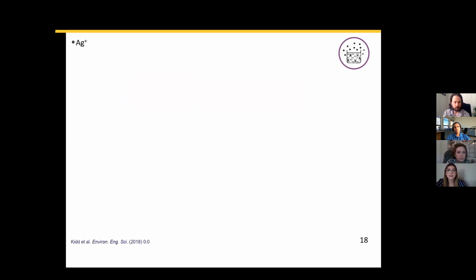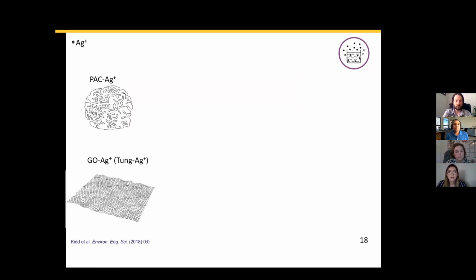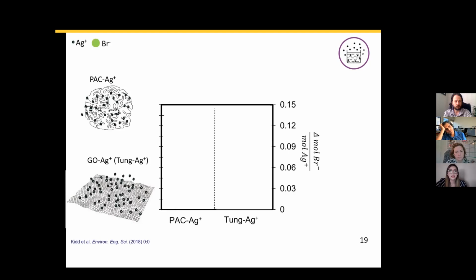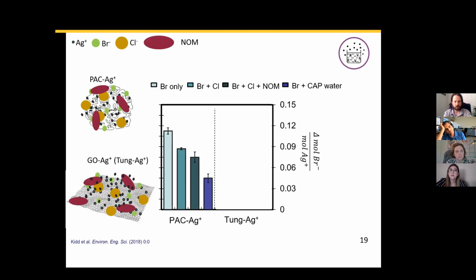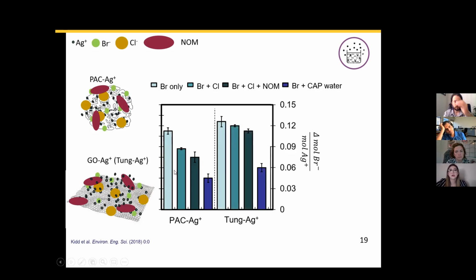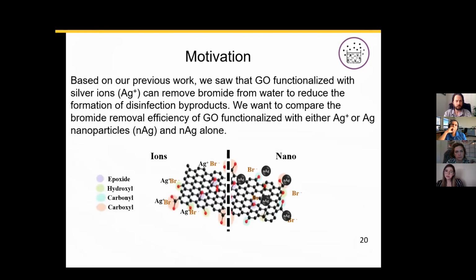One of our previous works actually dealt with comparing activated carbon with graphene oxide. And when we functionalized these with silver ions, we saw that as we increased the complexity of the water, the removal capacity of the nanocomposites actually decreased. But if we compare these two materials, we see that graphene oxide has a higher removal capacity than activated carbon. And this led to the motivation of our project. We know that graphene oxide functionalized with silver salt is a good material to remove bromide from water. However, what if we were to use silver nanoparticles instead of silver salts? So the whole motivation is, let's compare a salt versus a nanoparticle-based composite.